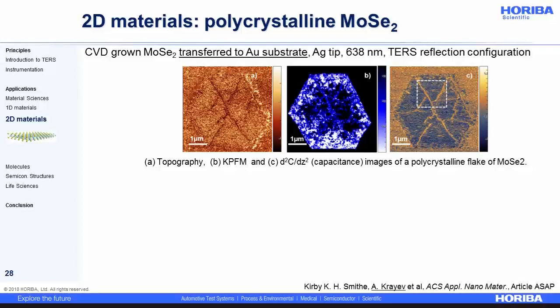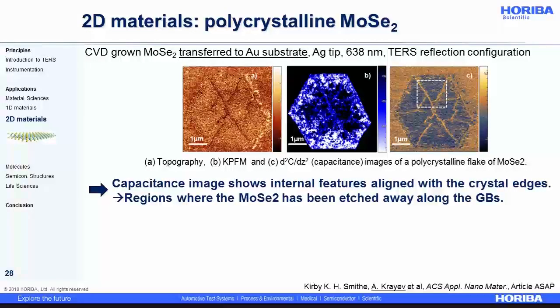So the molybdenum diselenide sample is now transferred from SiO2 to a gold-coated substrate using hot sodium hydroxide and a PMMA layer. You have the topography, figure A, the Kelvin probe force image, figure B, where we see some clear variation of the surface potential again, and the second derivative of the capacitance, figure C, of this polycrystalline flake of molybdenum diselenide. The capacitance image, showing again more contrast than the topography, reveals some internal features aligned with the crystal edges. So most probably the molybdenum diselenide has been etched away along the grain boundaries. And let's try to confirm that with a TERS map.